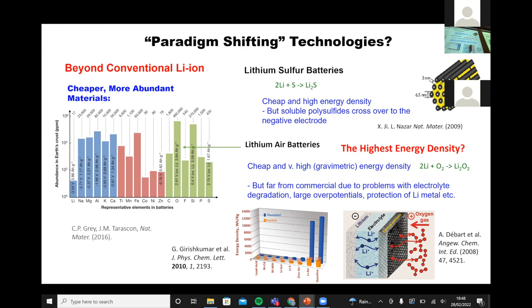With lithium-air, you take a gas and effectively do something like a fuel cell — the oxygen gets into the electrolyte and forms solid lithium peroxide, which is an insulator. When you charge, you've got to get electrons into the system to re-oxidize the peroxide back to oxygen, which is associated with very large overpotentials. The reaction from peroxide to oxygen goes via a superoxide — a highly aggressive radical that attacks the electrolyte — and you can also form singlet oxygen, which is also highly reactive. The challenge is to try to do this chemistry using redox mediators that can oxidize and reduce things in solution, and to find a catalyst that will speed it up.